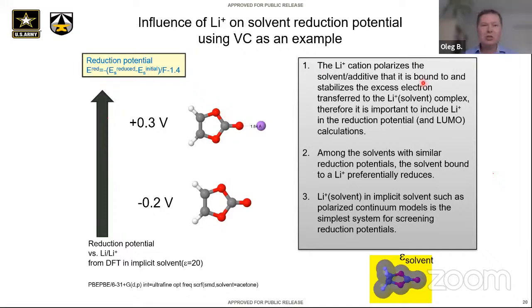Good, so let's continue to the other side. On the other side, we are going to use exactly the same thermodynamic cycles, and that got us a reduction potential as in the solvated reduced species minus initial, take a negative sign, divide by the Faraday constant, subtract 1.4. And keep again in mind that 1.4 could be 1.6 or 1.2 depending on the solvent, right? But for this purpose, we are going to use 1.4.